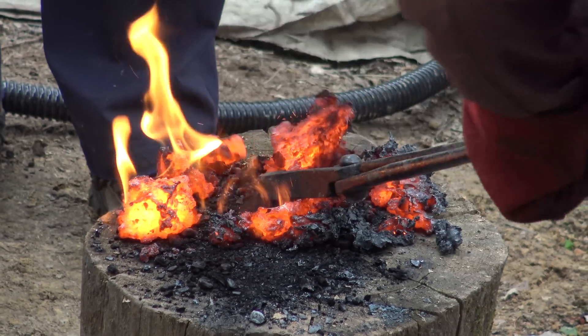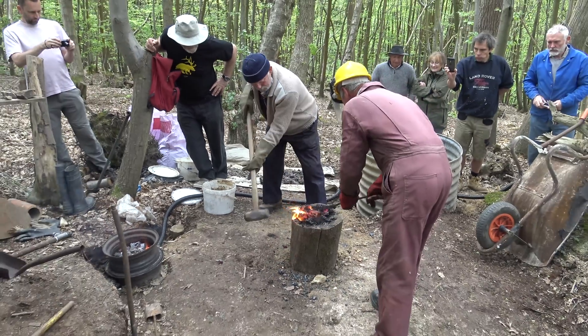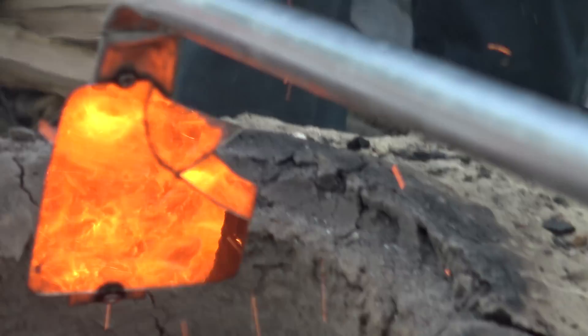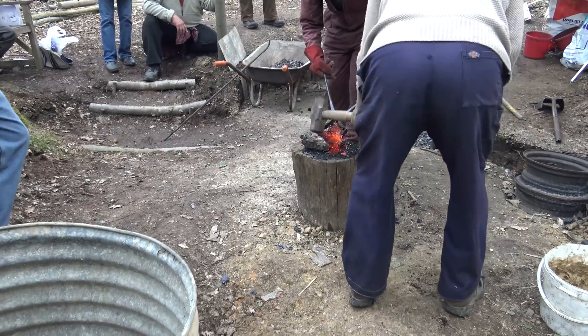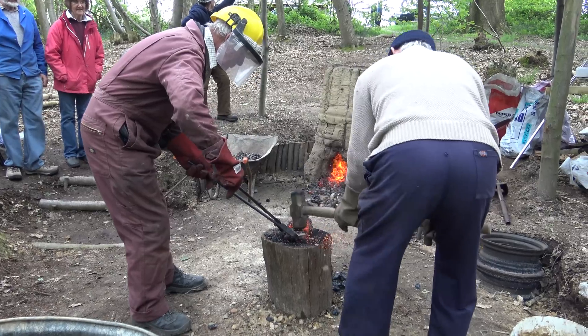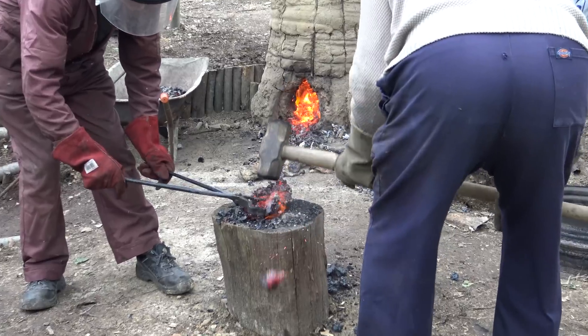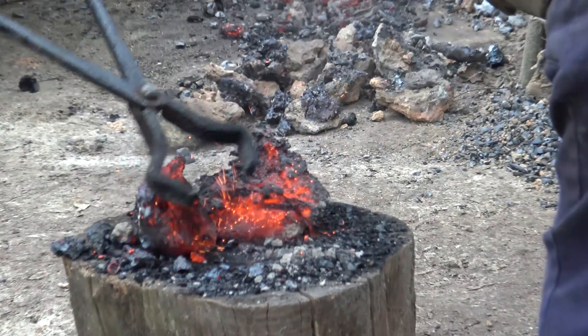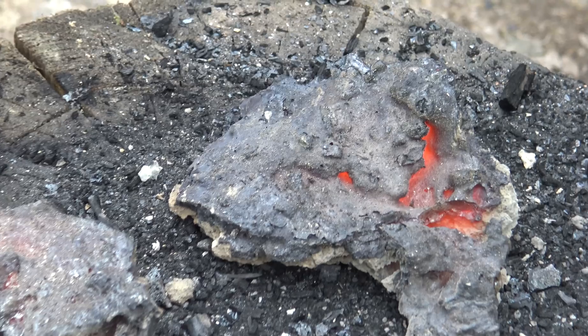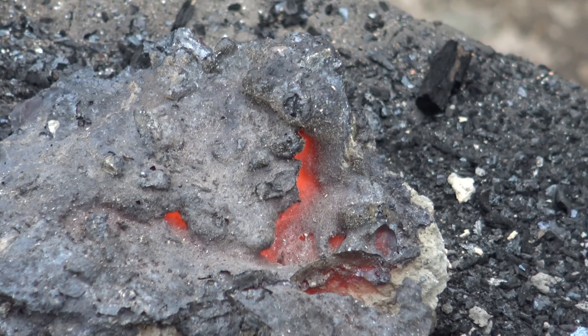The idea now is to beat the iron and try to concentrate it — get rid of the bits of slag and work the iron. This one wasn't as successful; the next attempt was. That is solid iron — we've got iron! You do tend to get it breaking up. It's like you've forged them back together. I mustn't hit it too hard — it's probably too much carbon in it. You'd have to use less charcoal.